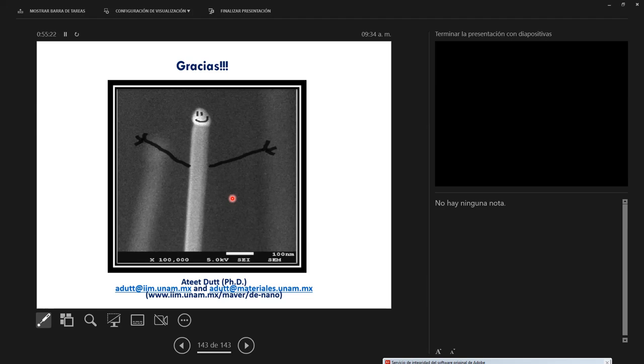Because if I know the interaction, if I know the bonds, I can increase the sensitivity. If it's the oxygen responsible for the interaction, let's increase the oxygen. Let's increase the defects of zinc oxide, the oxygen on the surface, and have the interaction. In this case, nanowires will be much more effective because they have higher surface area as compared to nanoparticles, which are zero dimensional. So yeah, we are doing those things. Again, the results are quite limited because it takes a lot of time to simulate these nanowires on the computational scale, but we are interested and we are doing some basic studies with those kinds of interactions.